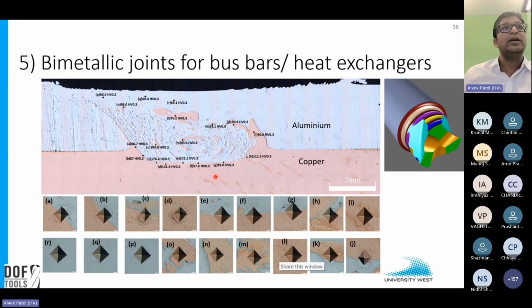So here you have a lot of intermetallics, as expected, and we try to monitor the hardness at different intermetallics, and we try to understand what's happening and how these intermetallics become hard. We found around 175 HV, and in some cases 200 HV hardness, against 95 HV for aluminum and copper. So these are very, very brittle intermetallics, and they are detrimental to the joint performance.